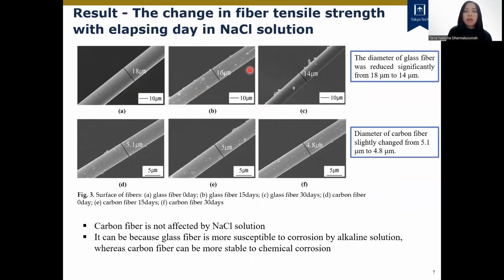In Figure 3, the upper one is the glass fiber, and the lower one is the carbon fiber, observed in SEM. They're using SEM to observe the surface condition. Basically, we can know the carbon fiber is not affected by the NaCl solution. Meanwhile, for the glass fiber, we can see that the diameter is reduced. So carbon fiber is not affected, and it can also be because glass fiber is more susceptible to corrosion by alkaline solution. Meanwhile, carbon fiber is more stable to chemical corrosion.